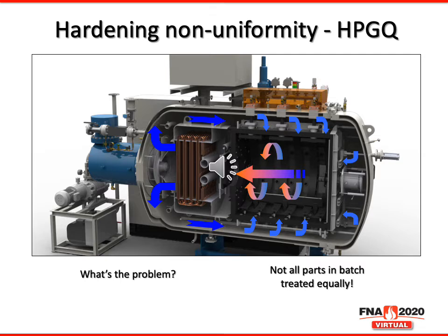Also, this allows for a high velocity at the exit of the nozzles going into the hot zone. This nozzle velocity, which is many times between 40 to 50 meters per second, which by the way is around the wind speed of a Category 3 hurricane, allows for deep impingement, infiltration of the gas flow into the load. Even with all these measures, we still have flow interruptions.